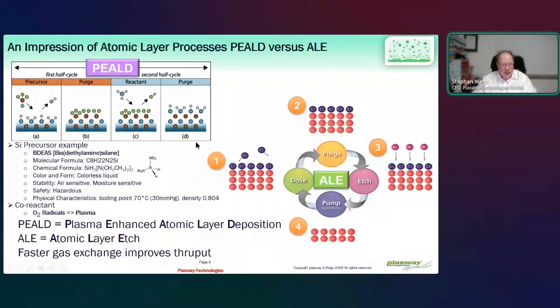So the basic concept of ALD is that you bring into your vacuum chamber first a precursor. This can be a complicated carbonized material, a polymer, and this sticks very nicely on the surface of the wafer. Then you need to purge, so everything needs to be removed. Then in the next stage, you bring in, for example, oxygen into your reactor to make an oxygen reaction on the surface, and then you need to purge again. So you already see a limiting factor when you would like to make it fastest: bring the gases onto the surface of the wafer in a good way, and on the other hand, you have to pump them away.